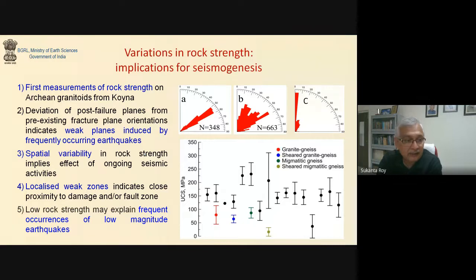On the top panel, you see that the deviation of the post-failure planes from the pre-existing fracture and fabric orientations indicates weak planes induced by frequently occurring earthquakes. On the rightmost panel, figure C, you have the post-failure orientations that we got from the laboratory measurements, and you can clearly see that in addition to these weak planes already existing, there are other planes along which the failure happened. The spatial variability in rock strength implies the effect of ongoing seismic activities, possibly. Localized weak zones indicate close proximity to damage or fault zones. And the low rock strength may explain the frequent occurrences of low magnitude earthquakes, because this rock is not able to accumulate a lot of stress, and therefore that may be an indicator of the frequent occurrence of low magnitude earthquakes in the region.